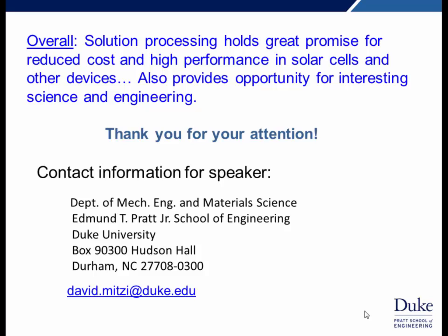You mentioned that the interface layer still got cadmium in it, cadmium sulfide. You mentioned some alternatives to that. How much progress has been made with a cadmium-free interface? Quite a bit, actually. In Japan, the sensitivity to cadmium is very strong. And so one of our partners, Solar Frontier, has a gigawatt production facility based on CIGS solar cells with a zinc-based buffer layer in the device. Working with them and also on our own, we've explored the zinc-based buffer layers and have seen not as good performance, but quite good performance, almost as good, let's say. Predominantly, the reason I don't mention that much during the talk is I can't give as many details, but yes, there is work on those other buffer layers.